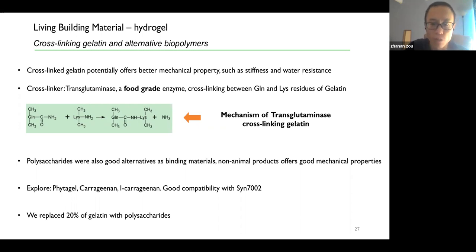And we also proved that they have a good compatibility with cyanobacteria 7002. So in this research, we actually did not completely replace the gelatin with polysaccharides. We only replaced 20% of it. The reason we're doing this is that gelatin still retains a vital gelation property.